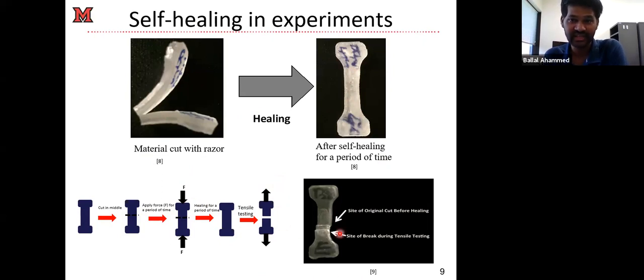So here is an example of how the material behaves after the tension test. This is the site where it was originally cut, but when they performed the tension test, they found that it breaks from another location. So it suggests that the material heals itself, because it's not breaking from the original location where it was cut. The spot where the material starts breaking is stochastic. Every time they did a test, they found that it breaks from different locations, which suggests something really interesting going on.